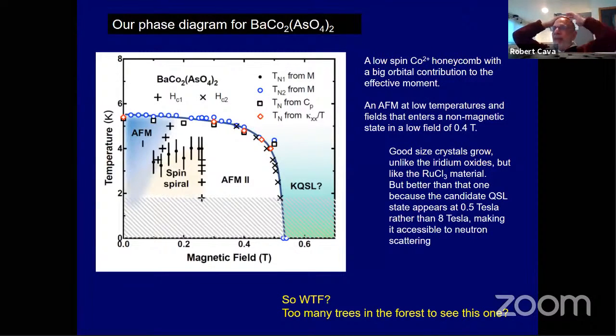So a phase diagram can get put together that looks something like this. So this shows the temperature-field phase diagram for barium cobalt arsenate with the honeycomb lattice of cobalt. And at 0.5 Tesla, the normal antiferromagnetic interactions go away. So this looks like, to me, or to most people, well, if you care to think about it, that it's become a quantum spin liquid at 0.5 Tesla below 2 Kelvin. So that would be a good thing.